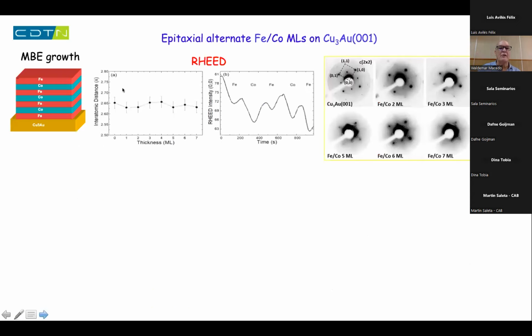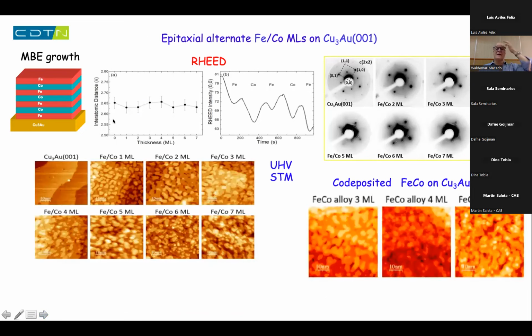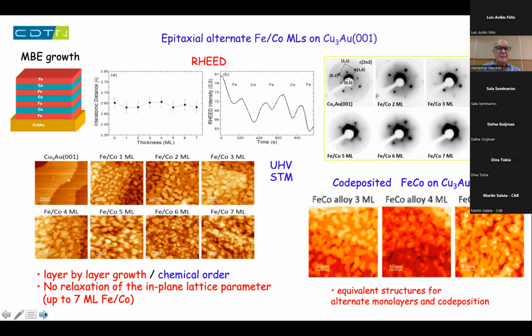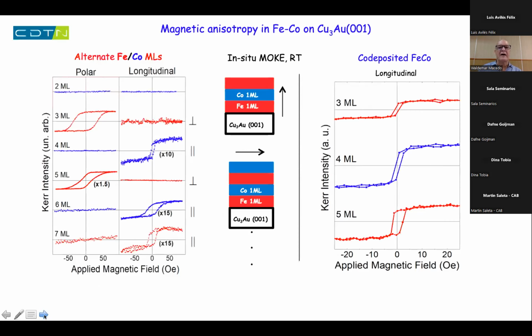And what we did is that we have grown then alternate iron cobalt monolayers on copper 3 gold, always 1 monolayer iron, 1 monolayer cobalt, and so on. And we did the growth, and this is here the results. We did the growth by molecular beam epitaxy. You see by RHEED that you have really the lattice parameter is the same as the copper 3 gold substrate. You have a layer by layer growth. And we compared the alternate iron cobalt monolayers with co-deposition of iron cobalt on the same copper 3 gold substrate. We see that from the structural point of view, they are equivalent. And let's see what happens with the magnetism. Let me show this slide.